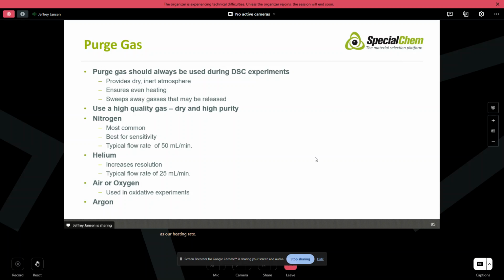Purge gas. Again, you should always use purge gas during any type of experiment. It's important that it's pure. You want dry and inert gas so that your gas is not going to react with the sample. Again, nitrogen, helium. In most cases, you can use argon too if you have an argon tank. And then air or oxygen if you're doing oxidative induction experiments.